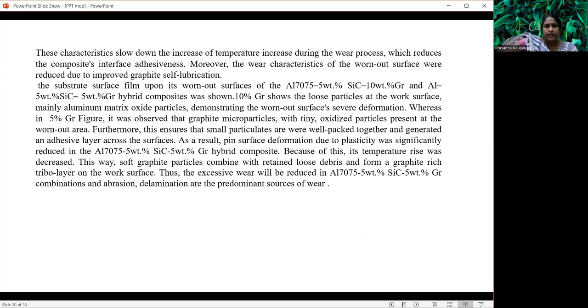graphite. In 5% graphite, it was observed that graphite microparticles with tiny oxidized particles are present at the worn-out area. Further, it ensures that the small particulates are well packed together and generate an adhesive layer across the surface. As a result, the plasticity is drastically reduced. Because of this, the temperature rise decreased, and this way the soft graphite particles combined with retained loose debris form a graphite-rich tribo layer on the worn surface. Thereby the excessive wear can be reduced.